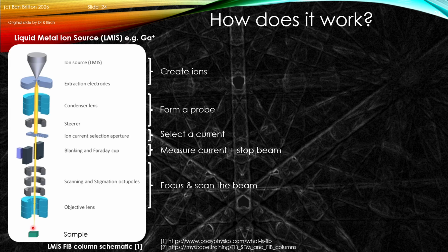And then we'll bring it into shape and to a point using the objective lens that will hit our sample. So we've got our ability to create our gallium ions. We can form the probe of those high voltage ions through the system. Once we've done that, we can select a current and typically a beam size. And then we can measure the current and stop the beam.